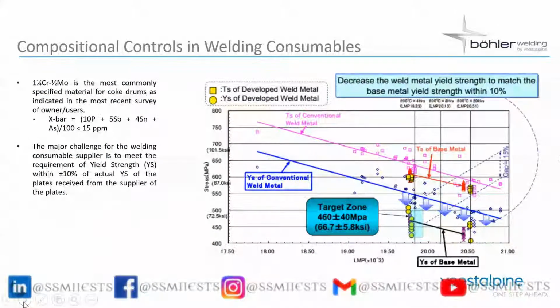And the challenge for us as welding consumables manufacturers was that we had a limitation from the fabricator that we had to develop consumables. It was 1 1/4 chrome half moly. That's fine, that is a common consumable, but with a yield strength matching the base material yield strength within plus or minus 10%, and this in consumable manufacturing is not so easy. So it was a big challenge, and it needed a full R&D project to arrive at this. And this graph shows the bandwidth within which we had to maintain the yield consistently, batch after batch of consumables, so that it was within plus or minus 10% of the plate material yield. Next.